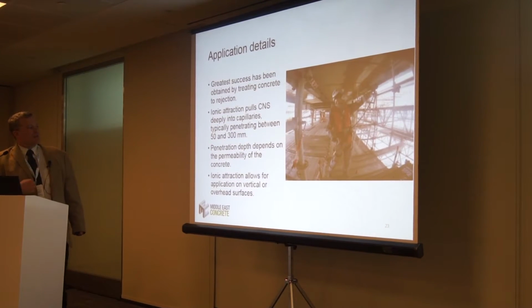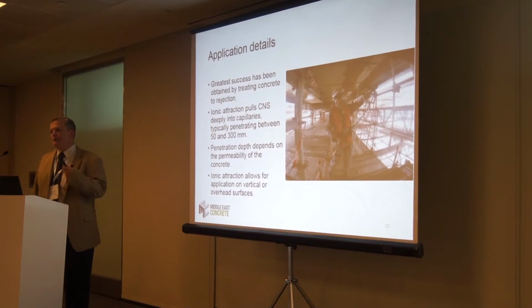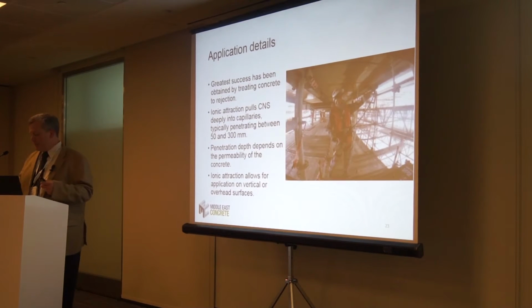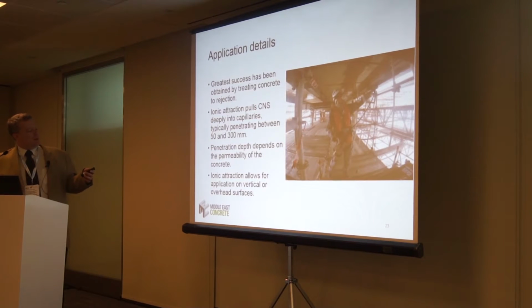So the penetration depth depends on the permeability of the concrete as well. We talked about so many things depending on the substrate permeability. But we've seen in the laboratory as well as cores taken from the field, typically somewhere between 50 and 300 millimeters is how deeply the product will go.